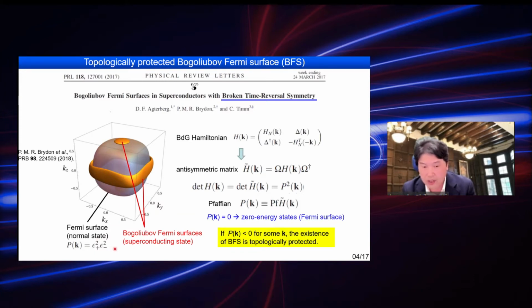But if you go into the superconducting state, what happens is that this Pfaffian usually becomes positive. But in the unconventional superconductivity, you may have Pfaffian equal 0, which corresponds to the nodes in the superconducting gap, or zero energy states. However, if they consider the superconductivity with broken time reversal symmetry, then they can find a solution with negative Pfaffian for some momentum space.